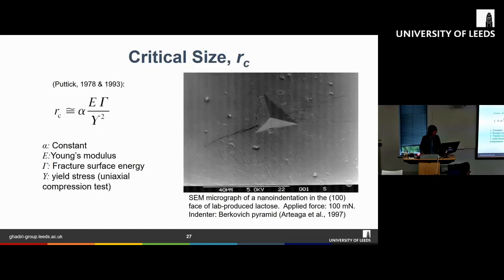With indentation, we can also use it to characterize the crack or the fracture toughness of a material. As an example, here you can see another impression made by a Berkovich indenter, and from the side you can see that the crack actually propagated as a result of that indentation. We can use this crack length to find a correlation with the critical size, which refers to the critical size that a material can undergo before complete failure.